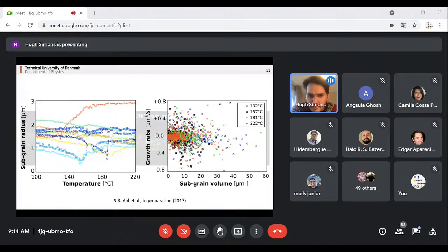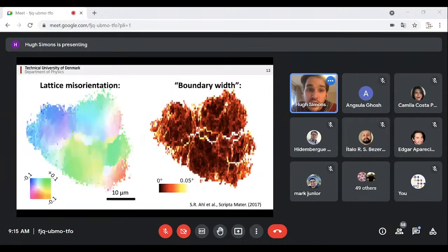Although this doesn't use microscopy, it gave us really insightful information, because it shows that there's no clear correlation between the initial radius of the subgrains and how fast they grow and to what extent they grow. This flies in the face of conventional wisdom in terms of recrystallization. And this is what motivated us to use the microscope to understand why this is the case. So this is what we did.